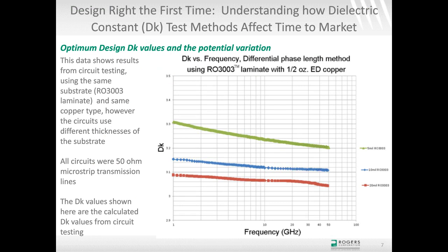What I mean by that is if you look at microstrip transmission line circuits, and that's the type of testing I'm doing here, again, the microstrip differential phase length method. In this case, the y-axis is the extracted dielectric constant of the material, and on the x-axis is frequency. The green curve is material using 5 mil RO3003 laminate, the blue curve is 10 mil RO3003 laminate, and red is the 20 mil thick. Really what it's showing is the thinner the circuit, the more it is affected by this copper roughness. And in this case, the copper roughness for this particular ED copper is about 2 microns RMS.